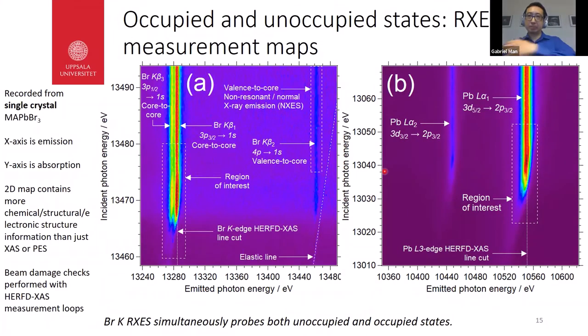Now I'll start showing some data here. On the left-hand side is the bromine K-edge high energy resolution X-ray emission spectroscopy map. On the right-hand side, this is the lead L3 edge map. And these are both recorded from single crystal methylammonium lead bromide. In the map on the left-hand side, we can monitor three emission lines simultaneously because the window of the spectrometer is roughly 250 eV wide. So we're looking at the bromine K beta 3, K beta 1, and the valence to core.